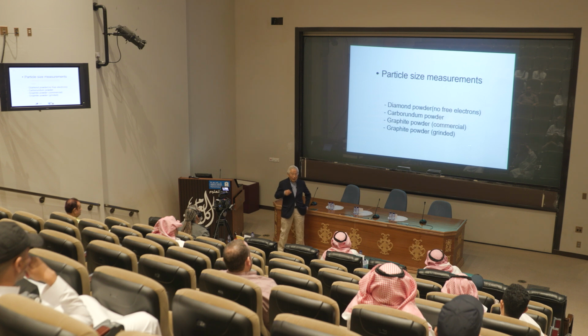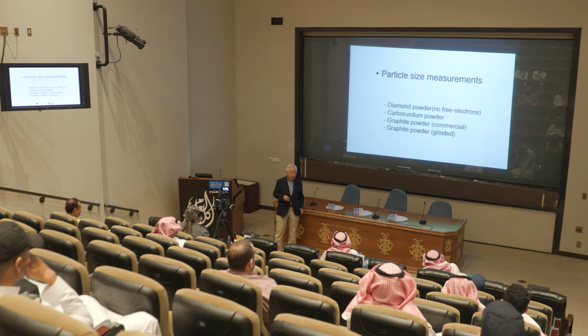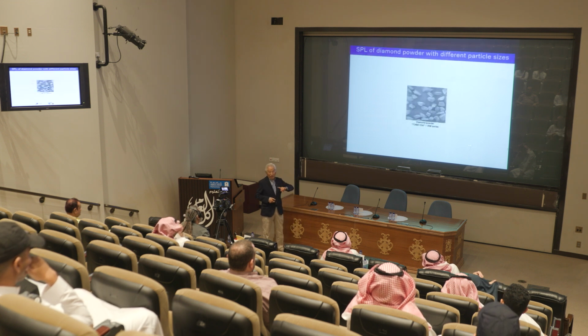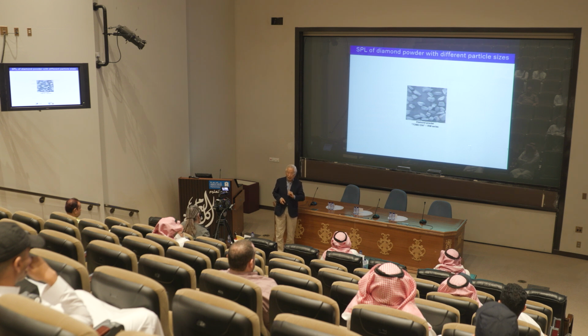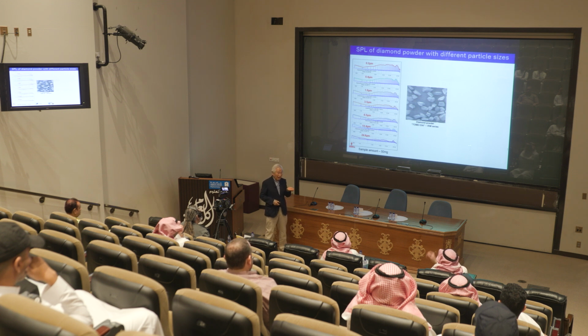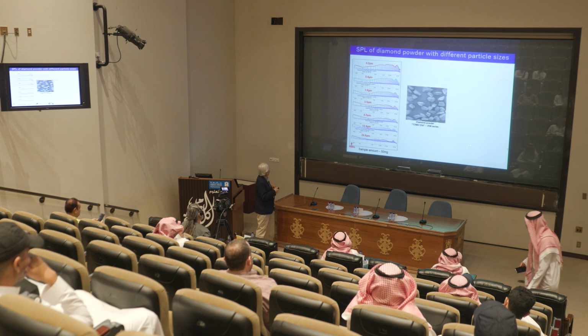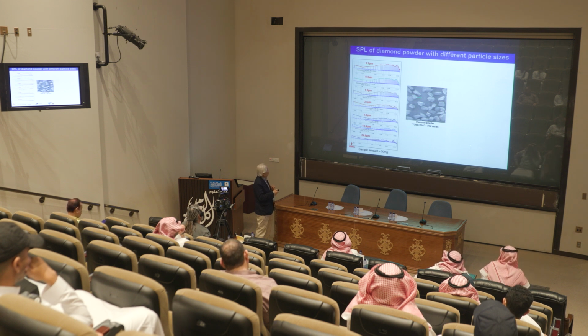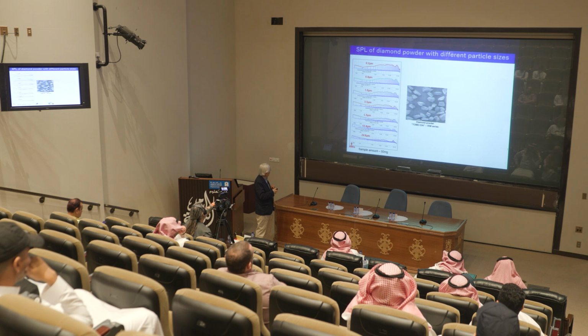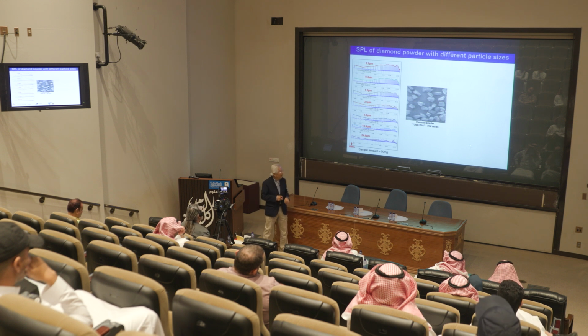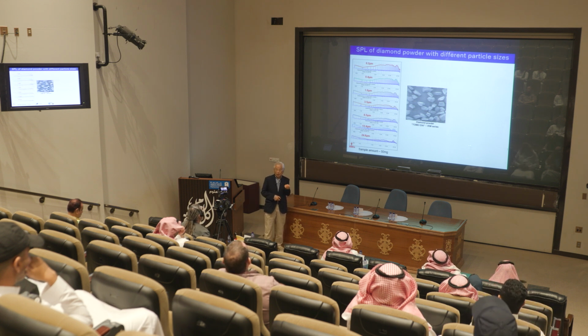Then go next. The next application is particle size measurement. Okay, if you change the size of your nanoparticle, you can also get some kind of information. This is diamond. Okay, this is a carbon material. So I prepared different particle sizes of diamond powder. And then I had 50 milligram of powder, and the size of those particles is changed. Okay, so let me see. Up here, the 0.2 micron diameter diamond powder. And as you go down, this is the biggest one, about 25 micron diameter powder. So the weight is fixed, 50 milligram, okay?